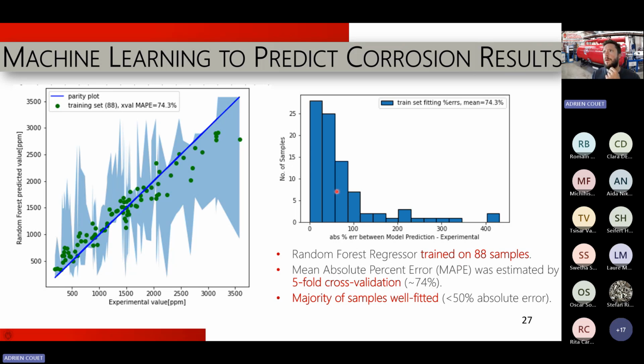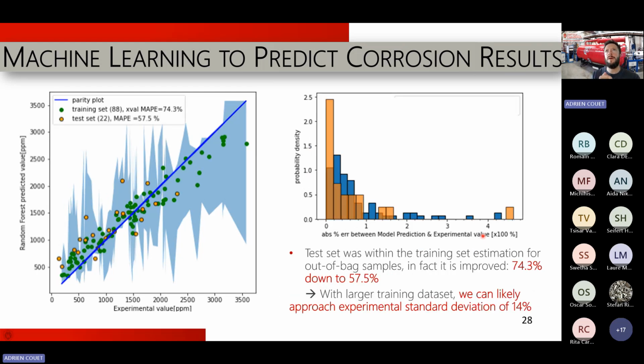Most of our samples are below 50%, which is good, right? We don't have a lot of outliers, so that's a good sign. And since we had more tests, about 110 alloys that worked pretty well, we were able to add 22 alloys that the machine learning has never seen, right? It's never been trained on them, not part of the 5-fold cross-validation. Then those 20% were relatively well predicted, as you can see from this plot. Most of them were below 50% error.